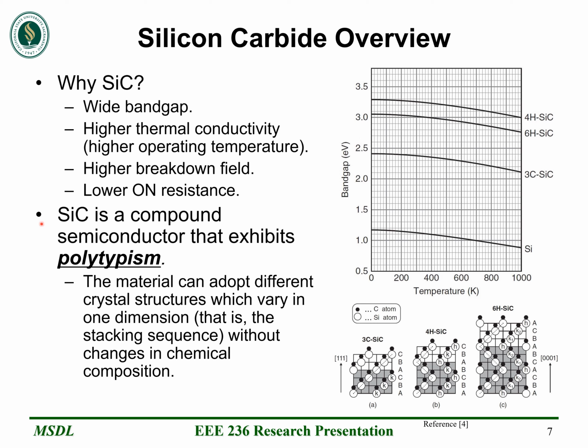Now, silicon carbide is a compound semiconductor that exhibits polytypism. What this means is that the material can adopt different crystalline structures which vary in one dimension, which we typically call the stacking sequence, without changes in chemical composition. So on the plot on the right, we have a ball and stick model of the different stacking sequences that silicon carbide can take. The naming convention is a number, which refers to the number of layers in the stacking sequence, followed by a letter which describes the shape that the stacking sequence creates in three-dimensional space.